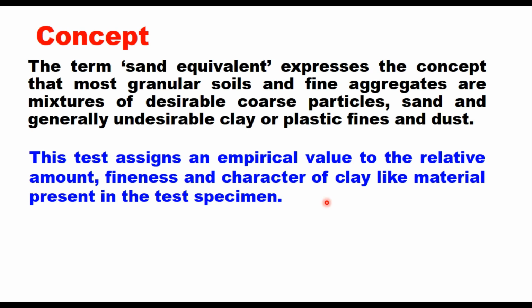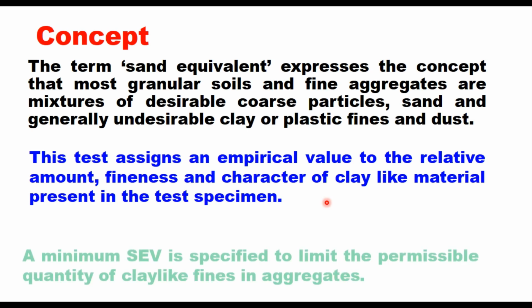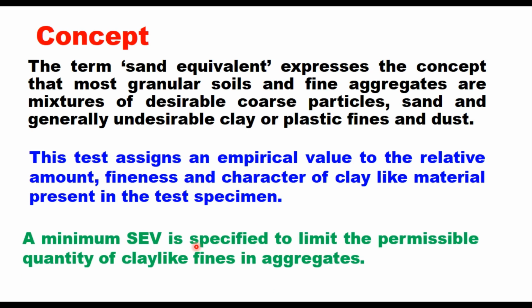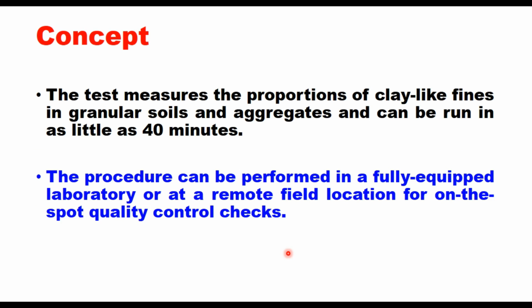And therefore, a minimum value of SEV is specified to limit the permissible quantity of clay-like fines in aggregates. For example, sand equivalent value for the fine aggregate to be used in bituminous layer should at least be 50. And this is a unique test and a very quick test that can be run in 40 minutes to measure the proportion of clay-like fines in granular soils and aggregates.